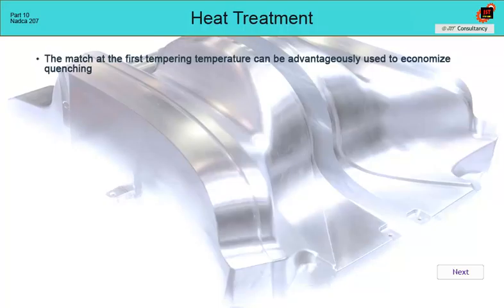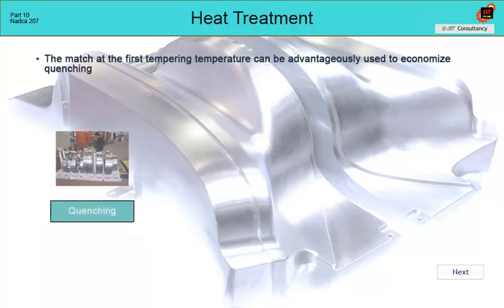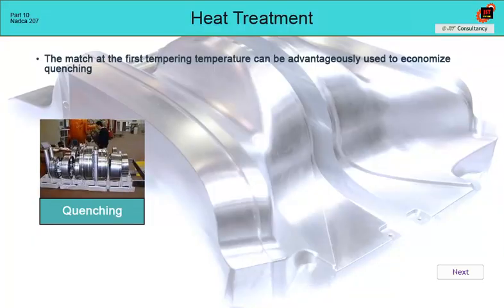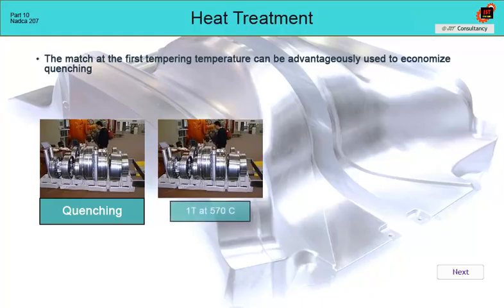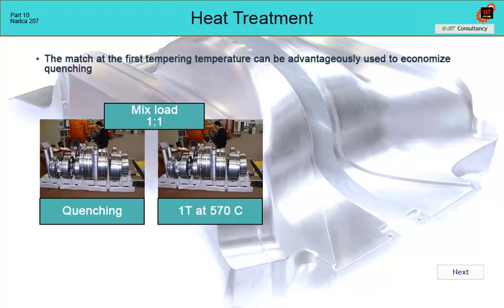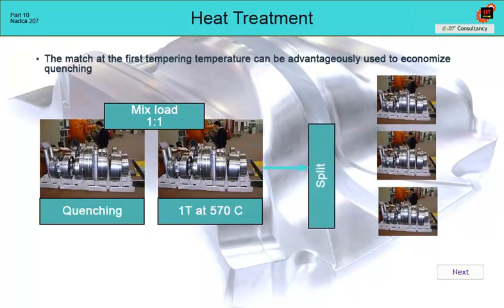The match at the first tempering temperature can be advantageously used for the economical hardening of mixed batches with parts made of the same or similar material with the same austenitizing temperature, processed to different hardnesses. After hardening, the batch is not split by material and by hardness, but is completely placed in a tempering furnace of the same dimensions as the hardening furnace to the first tempering temperature of 570 degrees Celsius. Only for the second tempering is the batch split into smaller batches according to material and hardness.